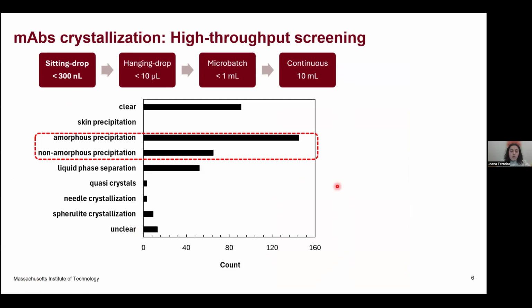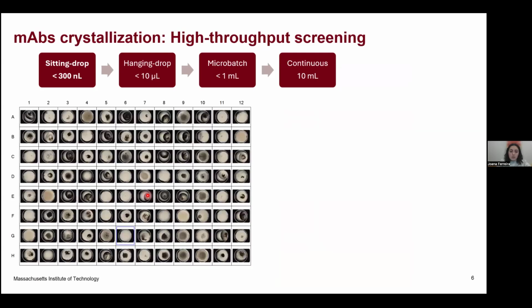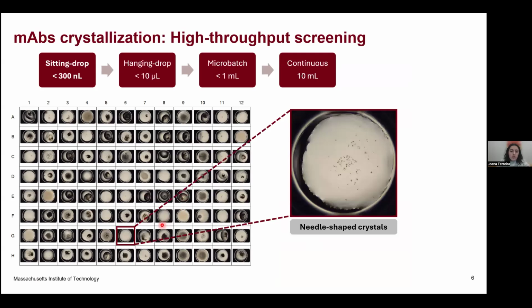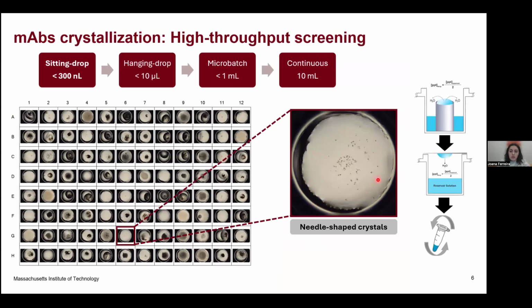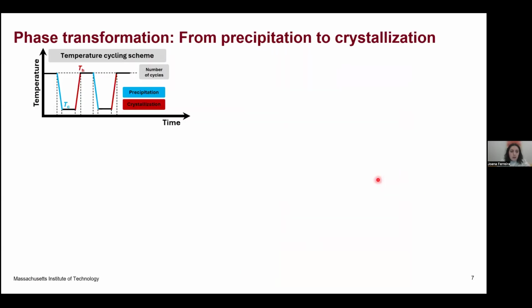However, most of the outcomes from our crystallization trials are mostly precipitates. As you can see here in this graph, most of the conditions end up with precipitation, and only a few of them give us crystals. Here I'm showing one condition out of thousands where we could see some needle-shaped crystals. So at this point, we are able to start thinking about scaling up, trying to crystallize at a larger scale.